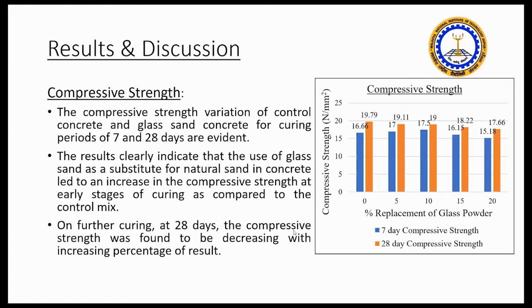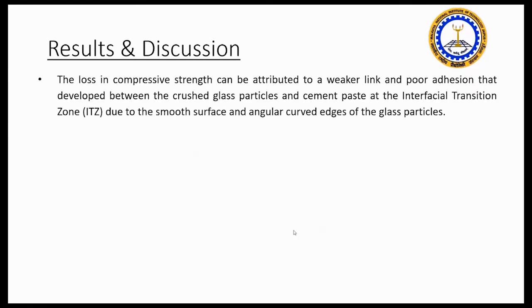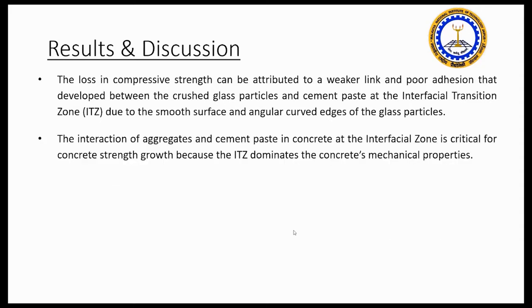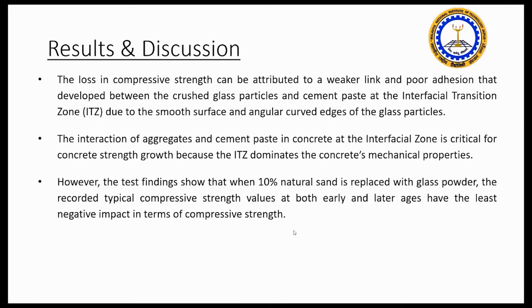On further curing at 28 days, the compressive strength was found decreasing with increasing percentage of glass powder. This loss in compressive strength can be attributed to a weaker link and poor adhesion between the crushed glass particles and cement paste at the ITZ, the interfacial transition zone, due to smooth surface and angular curved edges of the glass particles. The interaction of aggregates and cement paste in concrete at the ITZ is critical for concrete strength because the ITZ dominates the mechanical properties due to these linkages.